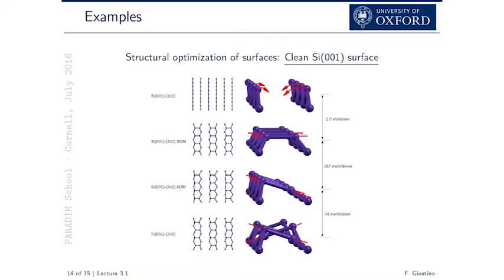And basically that's the same as in this picture here. So basically, if you slice this layer here, maybe I'll go, can you see me here, guys? If you slice this bit, you get this thing here. So now these are basically bonds all vertically aligned. That's very, very unstable. If you just start the calculation with this slightly asymmetric, it will all collapse. And the way it will collapse is into this structure.